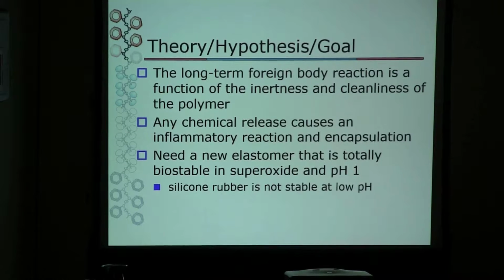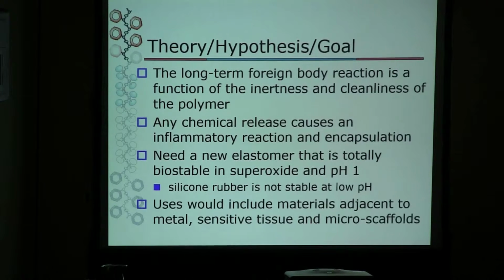So there's a need for a new elastomer that is totally biostable in superoxide and pH 1. And for those of you who use silicone rubber, it is not stable at low pH. It tends to depolymerize and release a cyclic molecule called D4. It's the precursor to silicones. And this is one of the problems that occurred with the shutdown of the breast implant industry, which happened about 15 years ago, because of the uncontrolled release of D4, which was believed to be steroidal.